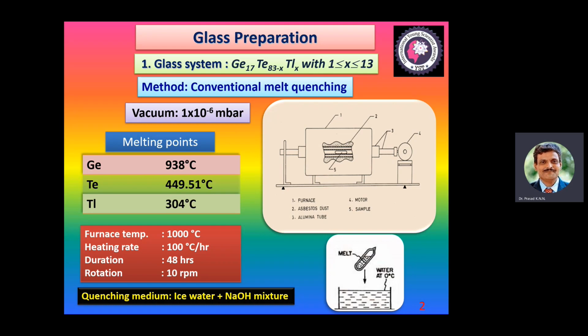Now the furnace temperature, as I said, is at 1000 degrees centigrade. This material is heated at a rate of 100 degrees centigrade per hour, for a duration of 48 hours, and the rotatory furnace is rotating at 10 RPM. Soon after the 48 hours, we got a bulk material, and immediately this bulk material was thrown into a mixture of ice water and NaOH, which is the quenching medium. As soon as we threw that, it became a solidified material, which is nothing but a bulk glass material. So this is how glass is prepared using conventional melt quenching in our studies.